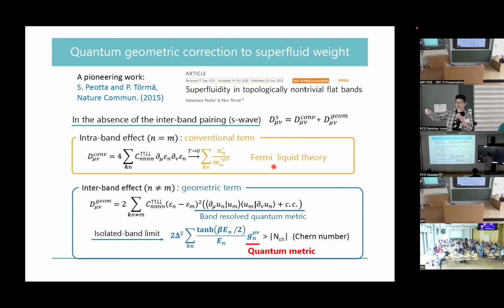One is described by the conventional mean-field theories. And in addition to this term, they obtained a correction from the quantum geometry. The quantum geometric term for the superfluid weight is generally represented by the band-resolved quantum metric like this. But when we consider the isolated band limit, where the energy bands are energetically separated from each other, this term is reduced to the quantum metric like this.